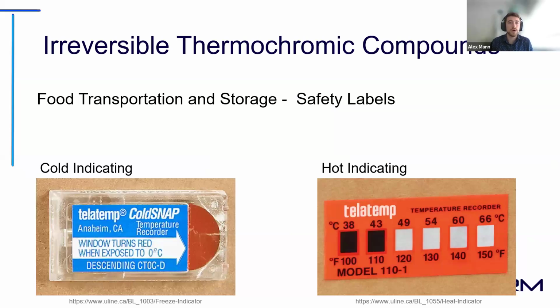So in terms of food storage, how is this useful? Well, this is really useful for safety labels. If the temperature drops below 0, the formation of ice crystals can damage the food, ruining the texture and the flavor. So there exist these cold indicating safety labels. So these are irreversible, meaning that even if the sticker briefly reaches the set temperature, the color change will be permanent. Now, some of them are regenerable, as we mentioned, but as you see, the temperature at which this occurs is way, way below ambient conditions, which you need special equipment to reach. So that prevents any tampering.